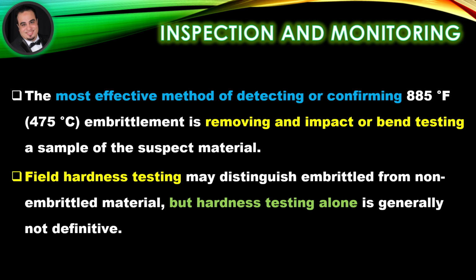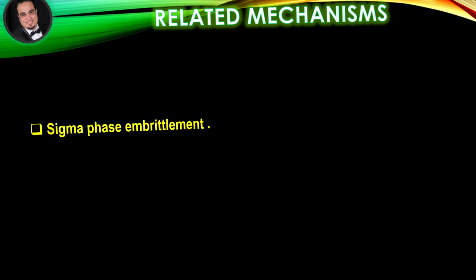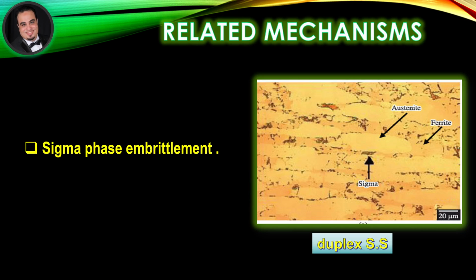The most effective method of detecting or confirming 885 degrees Fahrenheit embrittlement is removing and impact or bend testing a sample of the suspect material. Field hardness testing may distinguish embrittled from non-embrittled material, but hardness testing alone is generally not definitive. A related mechanism to 885 degrees Fahrenheit embrittlement is sigma phase embrittlement.